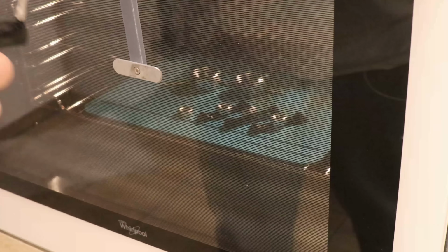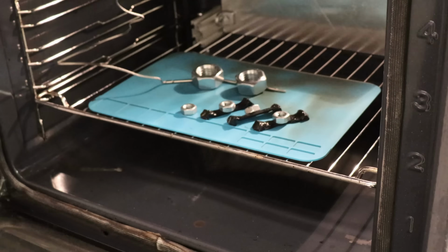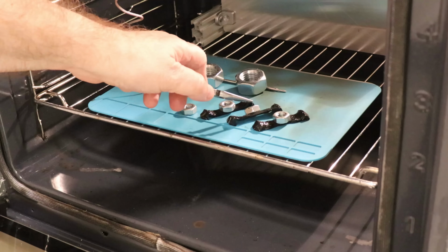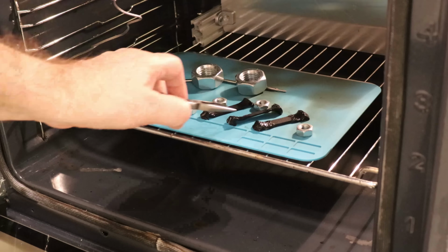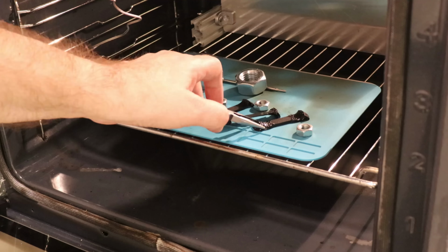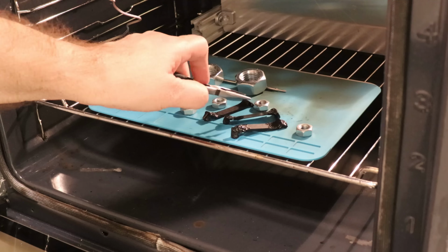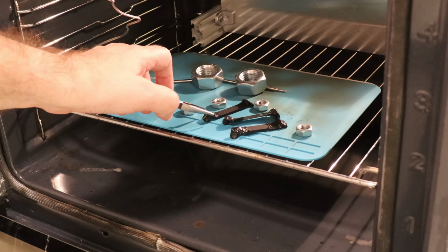And on these nylocs I couldn't see any deformation, and you will see it started to form very suddenly at 190 degrees Celsius. Looks like the surface starts with boiling, and after this they deform very quickly. 207 degrees Celsius, and I can see quite a lot of deformation. Wow. And currently I cannot see any bigger difference between them.